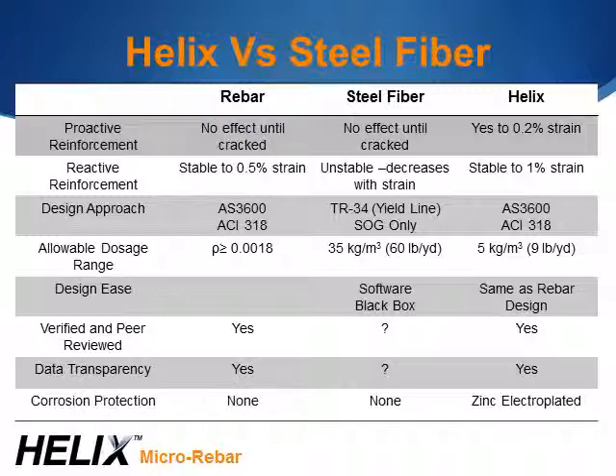And the reason they can be lower is because the bond is so much better, and that twisted shape is so much better. Again, we've changed the failure mechanism to untwisting from friction. The design method is very much the same as rebar design. It just requires a couple extra steps, looking at some tables, methods that are very familiar to engineers. It has been peer reviewed and tested against data.